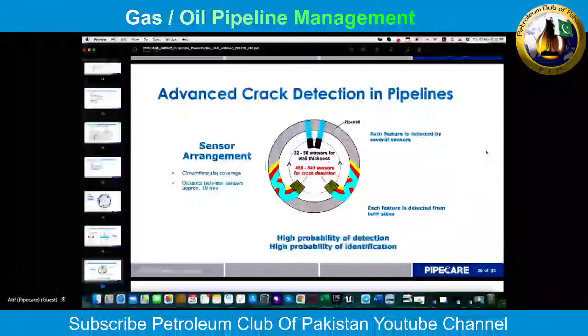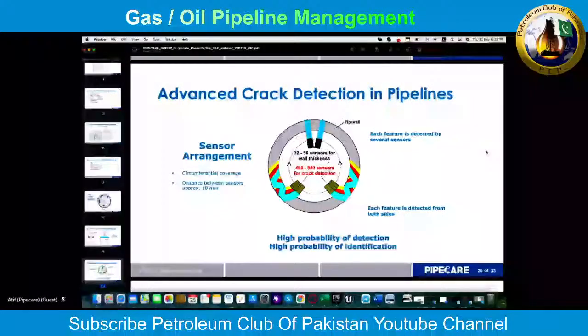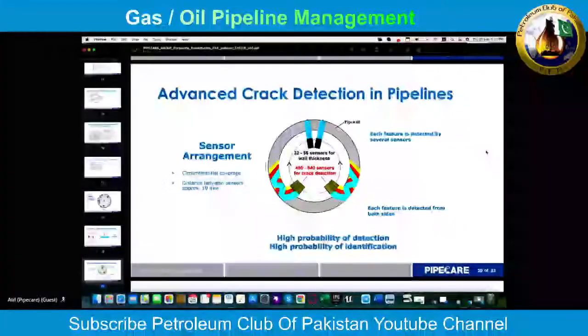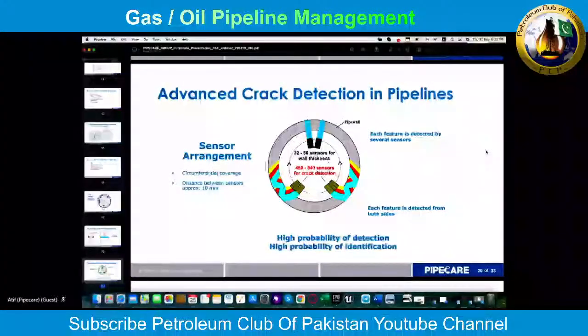And this resulted, of course, in much more repair recommendations, much earlier repair recommendations than was really necessary. And of course, it resulted also in higher expenditures. So now, with being able to give distinct depth sizes of cracks, the crack assessments are also much more accurate now.